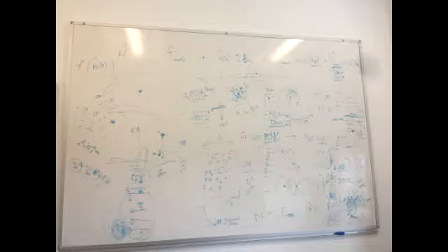And actually it can be even larger, because to represent this electron density, we do not just take a single level, but we create more orbitals for each of them so that you describe it more properly, so that you have all possible shapes of different orbitals as a basis on which you can expand any function. So it's like a Fourier transform. In a Fourier transform, you convert your function into a sum of sines. Here you get your wave function.